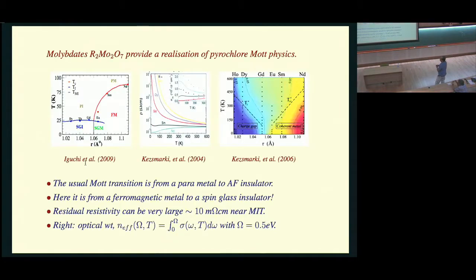So experiments. The experiments, unfortunately, are not a realization of the simple Hubbard model, but have additional degrees of freedom. So these molybdates, R2Mo2O7 with R a rare earth, live on a pyrochlore lattice. And if you vary the ionic radius, large is crudely like large hopping, small U by t, and this, if you wish, is your large U by t. So at small U by t, it's not a parametal, it actually is a ferrometal in its ground state.